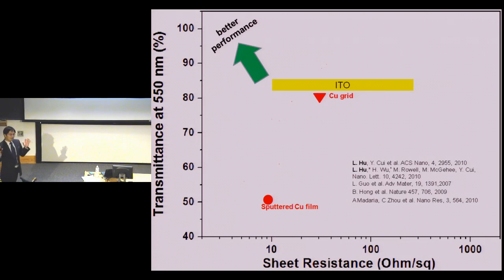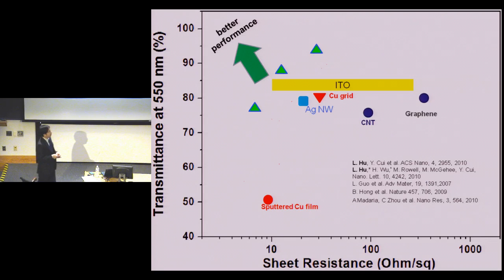So in the end, we're talking about how this electrode functions as a transparent electrode: transparency to photons, and conductance or sheet resistance to electrons. So this is the material ITO we're trying to replace or compete with. And this is the continuous copper film. And this is a copper grid from the literature. And you can see here, this is the performance of our transparent electrode based on continuous fibers with fused junctions. And we also compare with the best transparent electrodes from carbon nanotubes as well as from graphene. So you can see here, from the material design, we can achieve the best performance in terms of sheet resistance and transparency, which is very important for next generation solar cell or display applications.